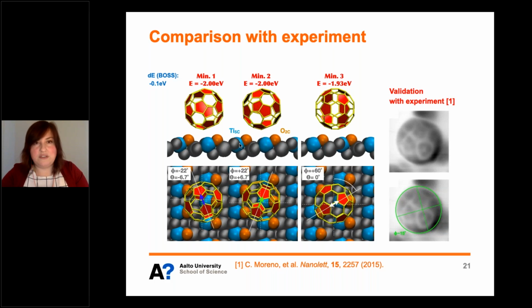Now, we used this surrogate model to extract the lowest energy points, and then we relaxed all degrees of freedom. And we found that the three structures with the lowest energy are these, 2 degenerate ones and one slightly different. Now, we also found that somebody had done experiments on this system and imaged C60 on the surface with quite a bit of atomistic insight. And you can see from the top that you get these oval structures with 4 different aromatic rings in the experimental images.